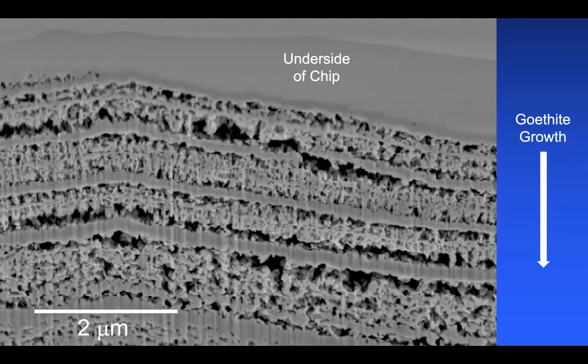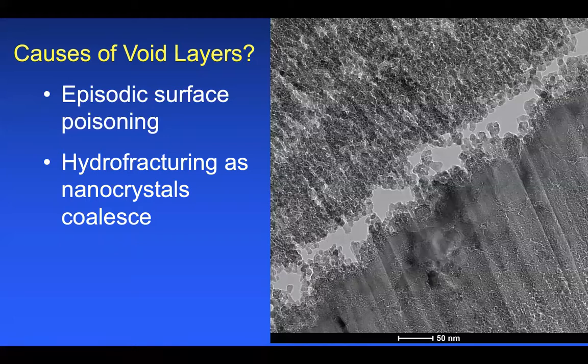These void layers can be very baroque in their appearance. Sometimes there's more void than there is goethite, and yet you still see this spectacular iridescence from these kinds of chips. And what we don't really understand is what is responsible for the void layer. I haven't actually published because I've been mulling this for two or three years, longer than I really should. But I think what I've finally concluded is that these are probably the result of surface poisoning.